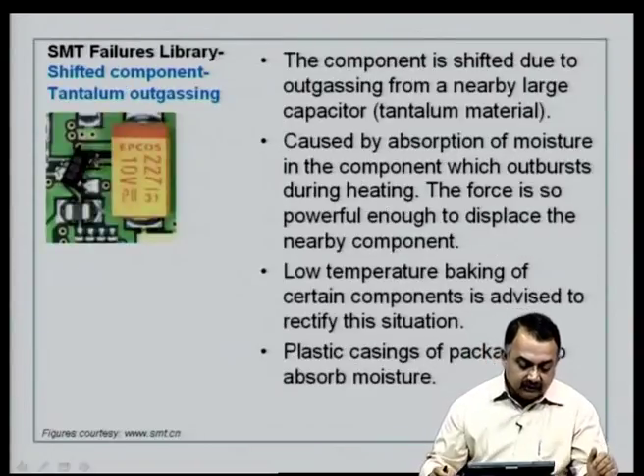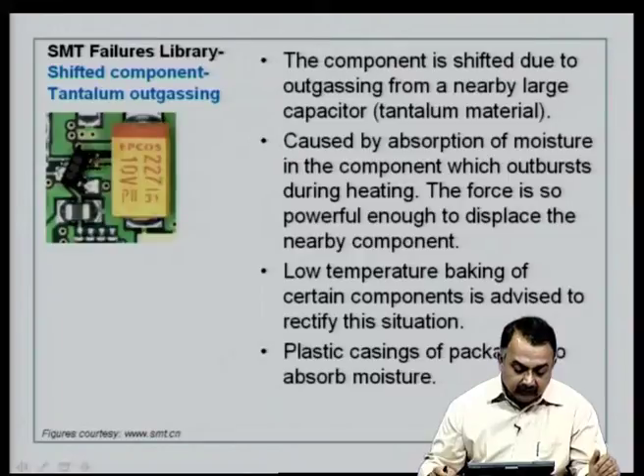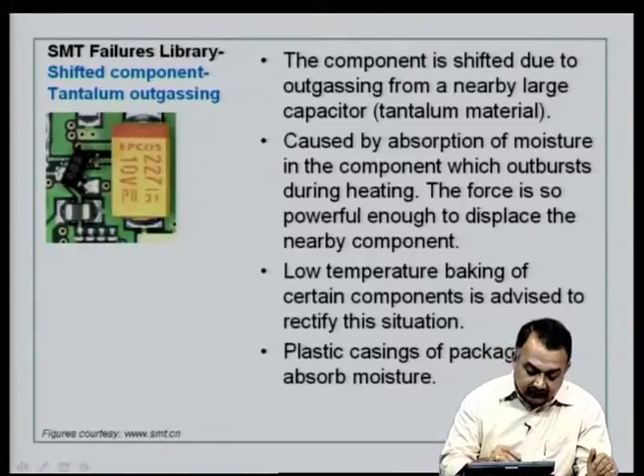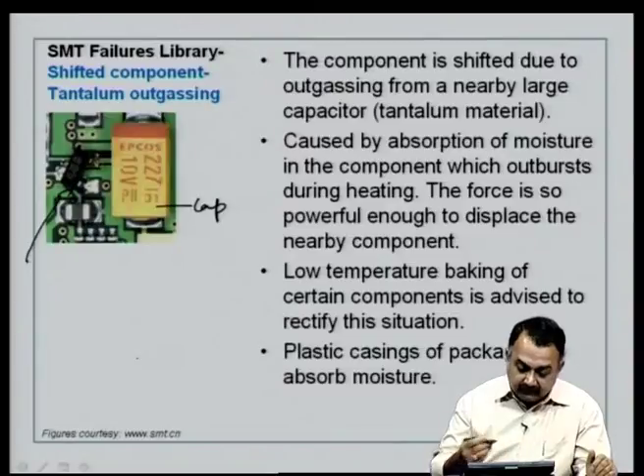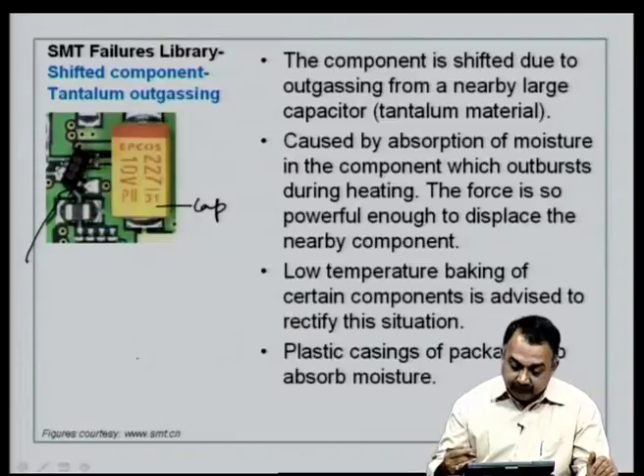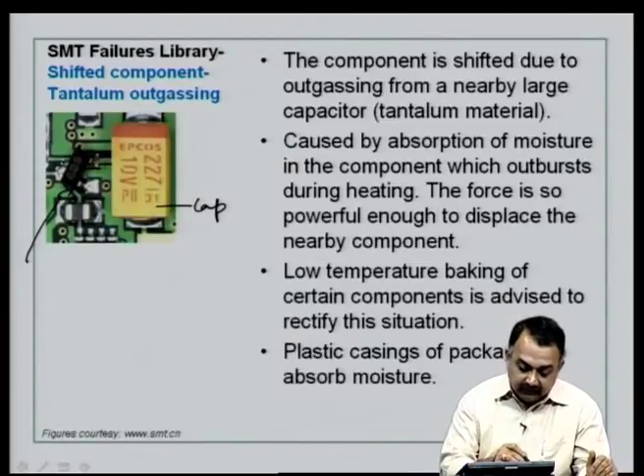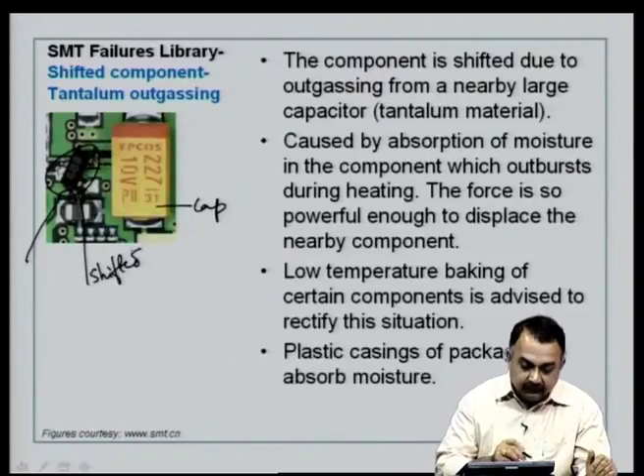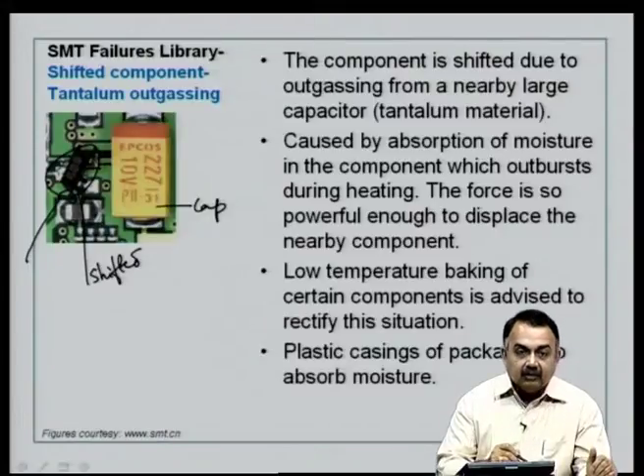Now, the other failure is a shifted component and tantalum outgassing. Here you can see there is a large tantalum capacitor, and here you can see a small component. Now, the solder paste has been dispensed, reflow has been initiated. During the reflow process, the component you see here has been shifted from its footprint due to outgassing of gases from this particular large tantalum capacitor.